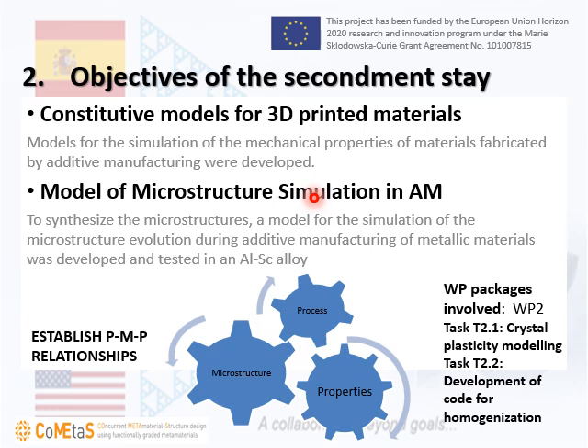For that reason, we must obtain this information either from experiments, in this case perhaps EBSD, or from simulations. Simulations in this regard have the advantage that they can generate data at faster and cheaper rates than experimentation. So for this reason, in the framework of this project, we have also developed a model for microstructure prediction. At the conclusion of the project, we expect to combine these two models and formulate what we call surrogate models by means of process structure properties relationships.